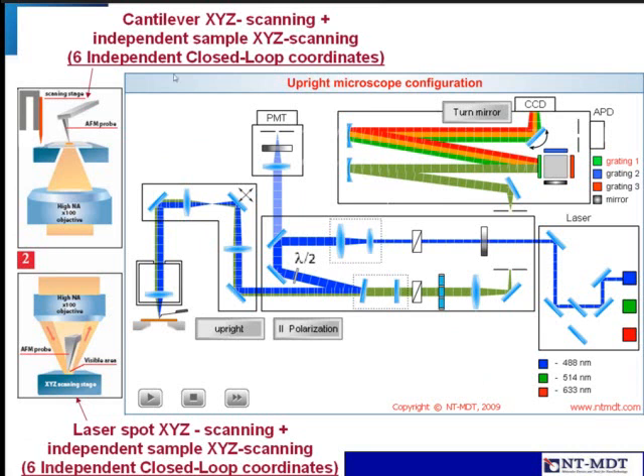This is the equipment doing this job. It consists of a confocal Raman system — a powerful confocal Raman spectrometer equipped with many lasers in the visible range, with a set of gratings, multiple detectors, polarizers, and beam expanders. The confocal pinhole localizes the area from which we collect the signal from the sample. With the confocal approach, the system reaches diffraction-limited resolution — typically about 200 nanometers in X,Y and about 500 nanometers in Z.